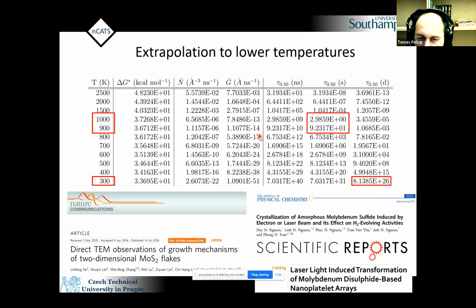And then you can use this model not for sliding, but to explain that the major thing here is diffusion. The most important thing is that we add energy into the system in terms of thermal energy through sliding. So it's not actually some shear or movement, it's actually the thermal input. And we can then look for other thermal inputs, for example, here where they use a laser to crystallize amorphous molybdenum disulfide, or actually TEM observation, because if you use TEM, of course, you can crystallize amorphous molybdenum disulfide. And we could see that we can really predict the energy you need to crystallize from our model. So we are very satisfied with that. So this was the first step to understand the formation of crystalline molybdenum disulfide as a result of sliding. And our conclusion is that it is mostly a process driven by diffusion and therefore by thermal energy input.